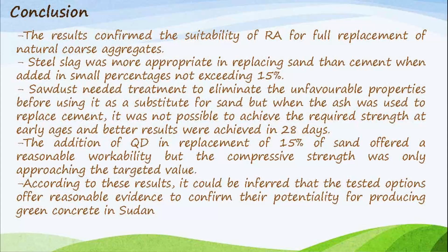So sawdust needs treatment to eliminate the unfavourable properties. The addition of QD replacing 15% of sand offered reasonable workability, but the compressive strength was only approaching the target value. According to these results, it could be inferred that the tested options offer reasonable evidence to confirm there is potential for producing green concrete for Sudan.